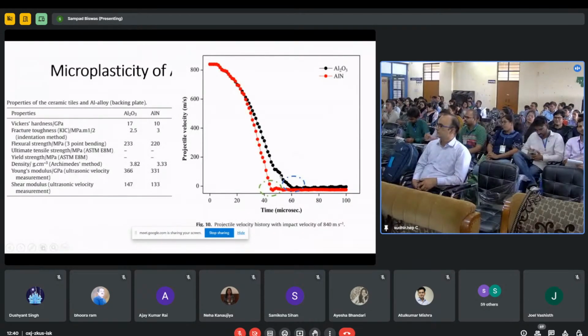Now if you look at this, you can find that there are two areas. This is the maximum velocity of the bullet. It is going down. And in these two materials, where it stops, this time is different. In one material, it is stopping within 42 microseconds. The other one, it is stopping at a much longer time. So this time difference plays on the property of the ceramics. Here comes the question of ductility within the material. So if you can increase the ductility of the material, you can get a lot of energy absorption as well.